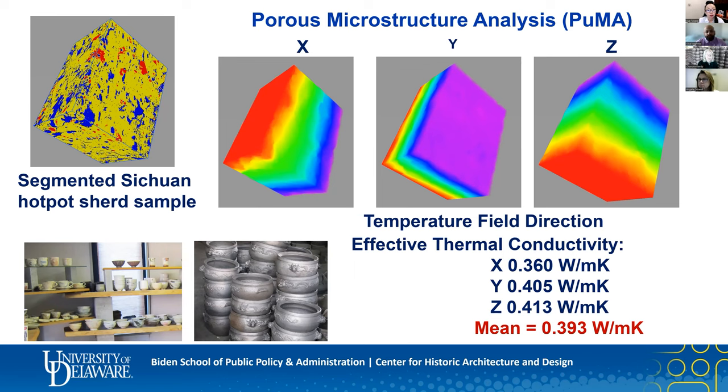You mean the amount of matrix? Well, you can do that in the segmentation process in image analysis, because the density of the matrix is going to be very distinguishable from that of the pores and of the particles that you find in there. Okay. If you want to identify what the matrix is, which clay minerals you have there, then you need to do another method, something like XRD, FTIR, Raman spectroscopy. Okay, so other techniques should be involved in that as well.